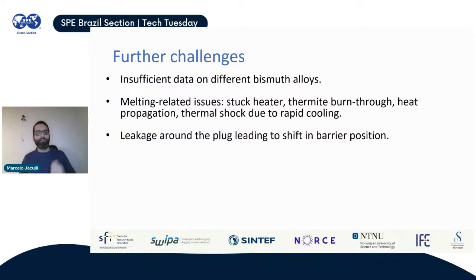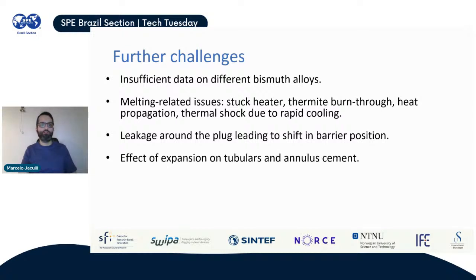We could have some problems when setting the plug. If you have some leakage around it while the alloy is still solidifying, you could have some shift in the barrier position. The plug might move from the intended position, and then you don't place the barrier where you want. It's kind of similar to what also happens with cement. Sometimes in some cement jobs, you are unable to put the cement in the position that you wanted and to reach the top of cement that was expected. So the same could happen here when setting this plug. And then you have the effect of the expansion on tubulars and the cement behind the casing, which I already addressed in the previous slide, but it's a concern here that needs more investigation.